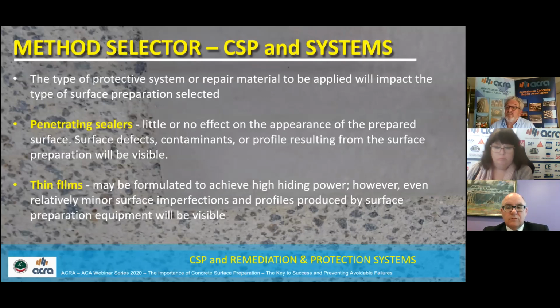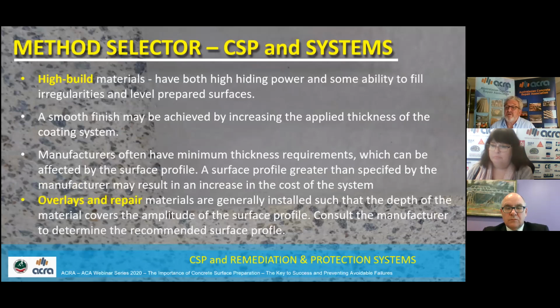The type of protective system or repair material to be applied will impact the type of surface preparation selected. For example, penetrating sealers have little or no effect on the appearance of the prepared surface. Any surface defects, contaminants or profile resulting from the surface preparation will be visible. High build materials will have both high hiding power and the ability to fill irregularities of the surface. A smooth finish over higher profiles may be achieved by increasing the thickness of the coating system. Manufacturers often have minimum thickness requirements, which can be affected by surface profile. A surface profile greater than that specified by the manufacturer may result in increased costs through more product.